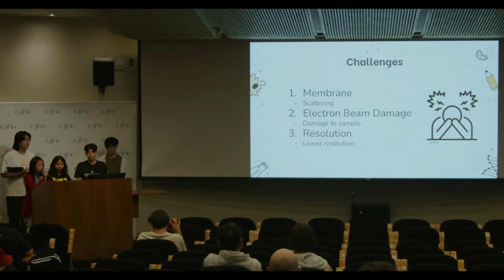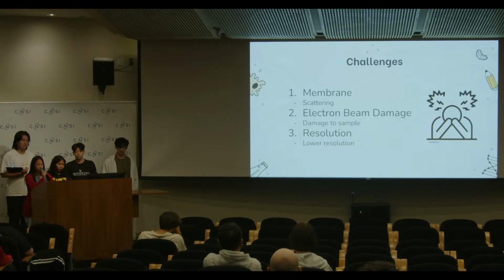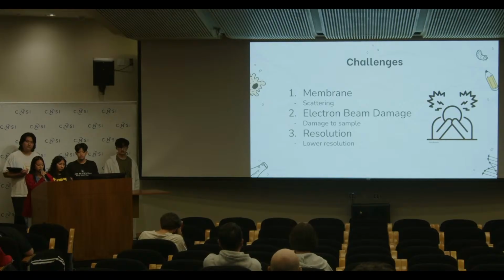The last challenge is resolution. Liquid cell TEM results in lower resolution than other techniques. The electron beam must pass through thicker material, and interaction and scattering of electrons within the liquid can degrade resolution.